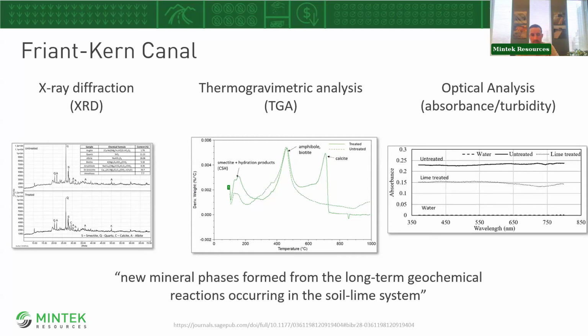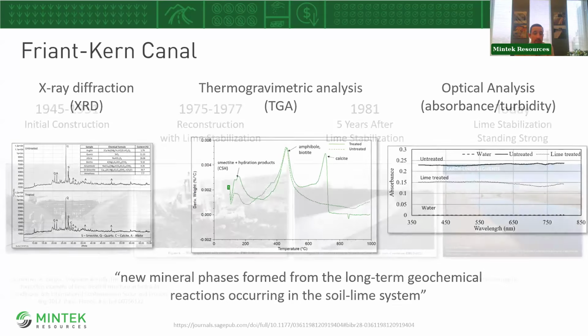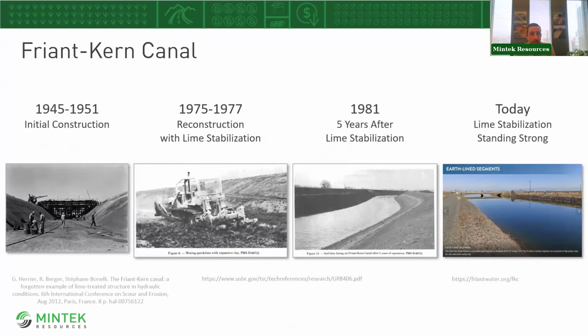those needle-forming cementitious compounds. On the right, the optical analysis, a higher absorbance intensity is a direct function of turbidity, and you can see a clear drop in the turbidity of the lime-treated soils, which is indicating that the dispersive nature of those native soils was controlled, making them less prone to erosion, which is essentially why we can still see those imprints of the pad foot roller, or sheepsfoot, excuse me.